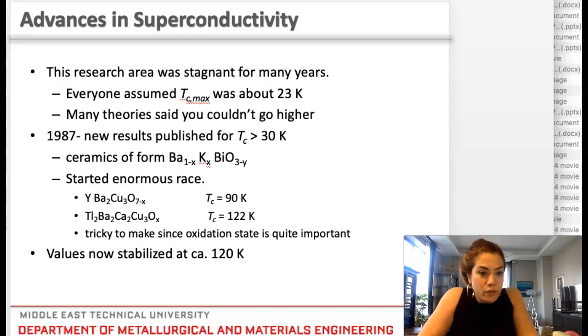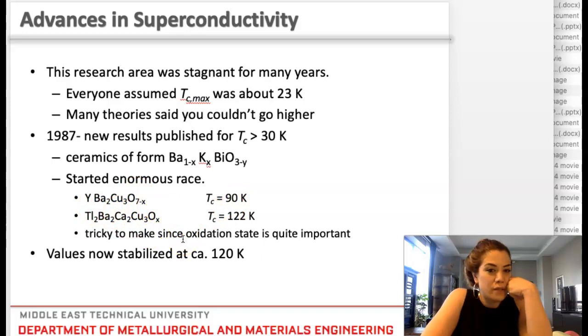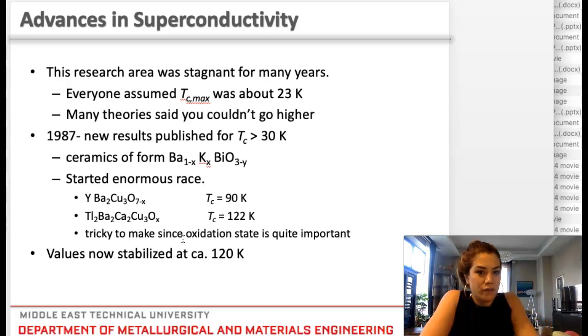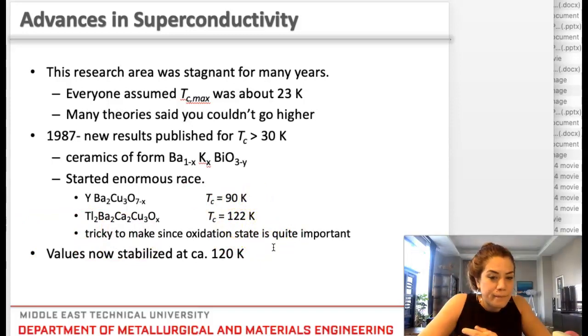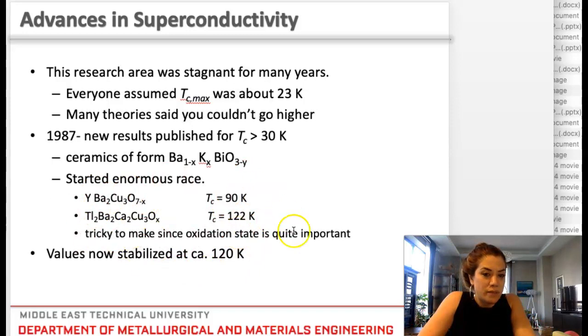So this kind of research is still carried out, but later in 1987, above 30 Kelvin, different forms of barium, copper, yttrium oxide ceramics exhibited such superconducting behavior. For example, for this compound the critical temperature was 90 Kelvin, and for this compound it was 122 Kelvin. You still have to cool it down, but you can use a relatively cheaper medium, such as liquid nitrogen, to obtain superconductivity for these materials. So there is still some research going on, and a large opportunity out there to find higher transition temperature superconductors.